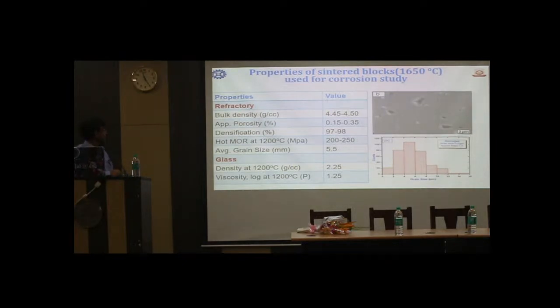So these are the typical properties of the refractory. The bulk density is 4.45 to 4.5. Apparent porosity is very low, it is 0.15 to 0.35. And densification is 97 to 98%. Average grain size is 5.5 microns. And the glass density is 2.25 at 1200 degrees centigrade, and viscosity 1.25.